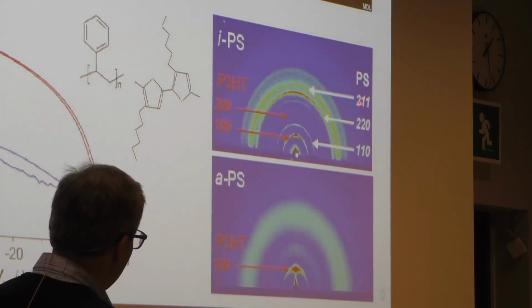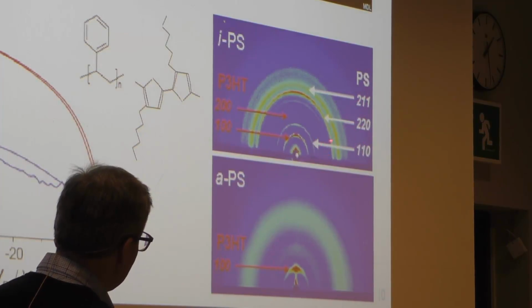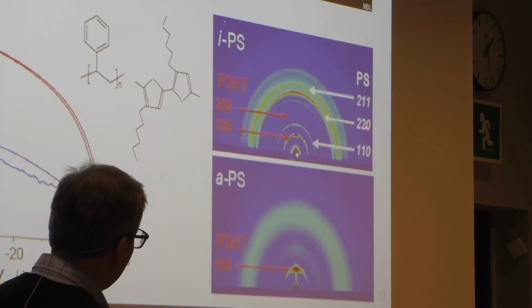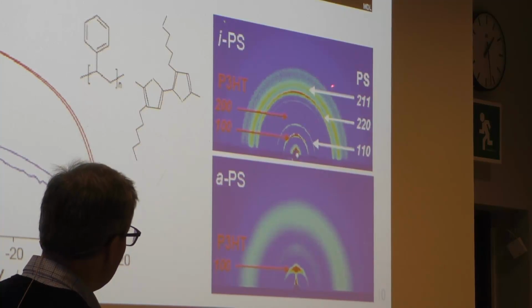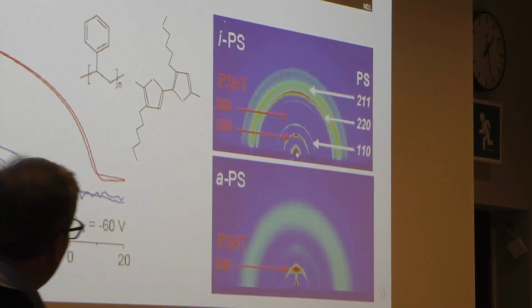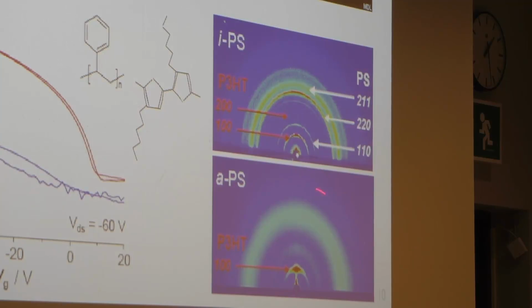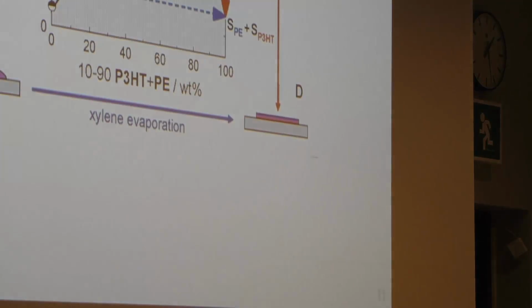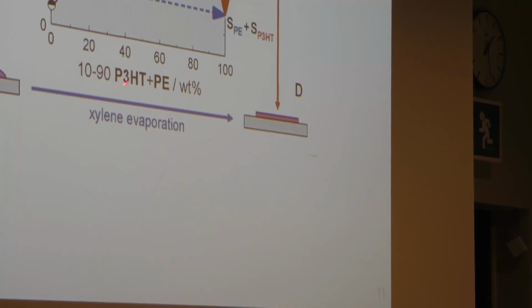And it's a rather simple exercise in this case to figure out that these are the 110, 220, and 211 polystyrene peaks, and we also see a bit of the polyhexyl thiophene, whereas in the atactic case, not surprisingly, the polystyrene is not showing any crystalline peaks, but you can see that also the signal from the polyhexyl thiophene looks very different.